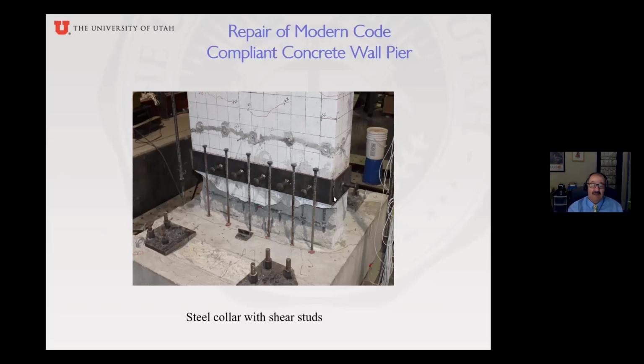In fact, this steel collar can be built very easily for those who know how to weld, by just welding and letting the weld cool down. When the weld cools down, of course, the steel tends to shrink and it clamps onto the concrete. So there's nothing to it. There's nothing else holding up this steel collar. These studs poking out here, they will grab onto the new grout that you pour inside the shell.